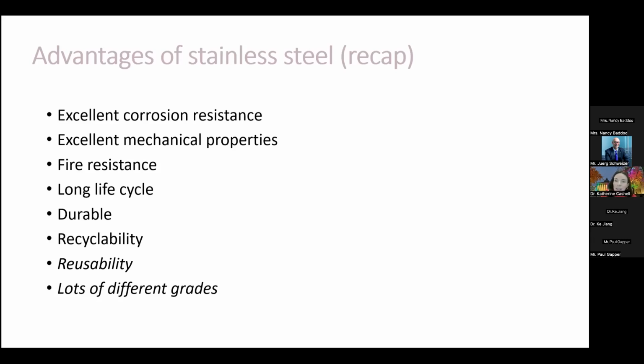Excellent fire resistance, so it tends to behave a bit better than carbon steel during a fire event. A very long life cycle, which is of course linked to the durability. Fully recyclable when it's bare stainless steel, of course, that's a bit trickier for rebar. And reusable. I have those ones highlighted because they're less relevant to the reinforced concrete.